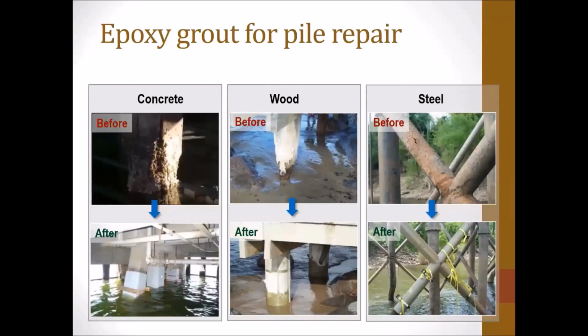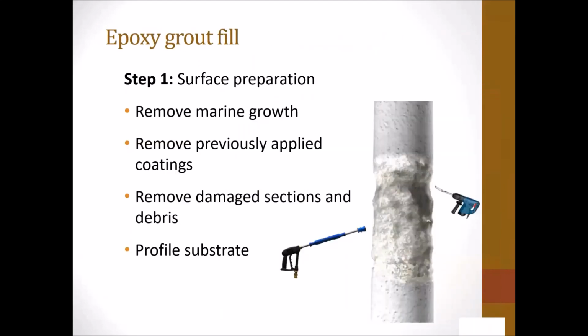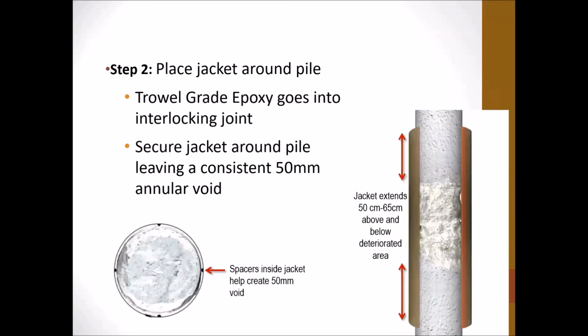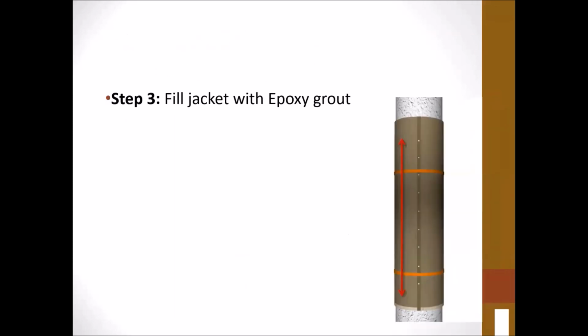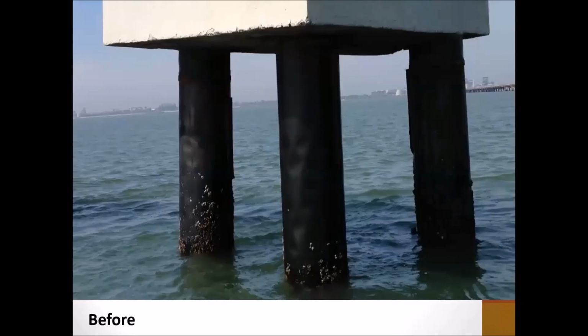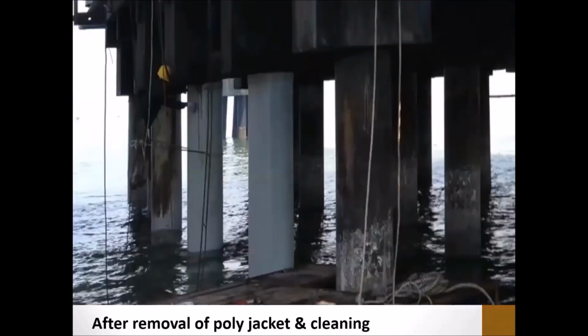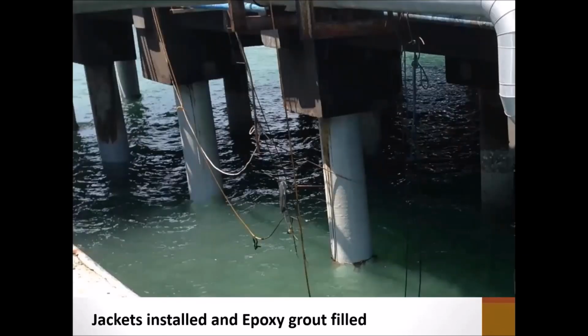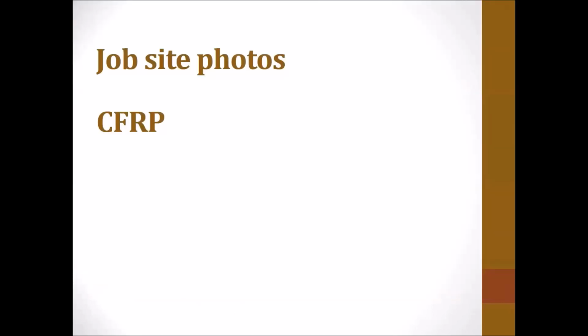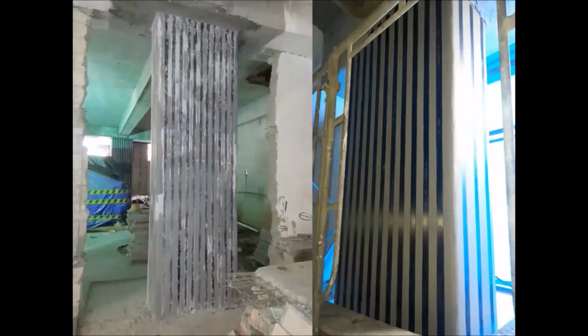So we can use epoxy grout for pile repairs. Basically we have to think about that only. We can use the fiberglass jackets after the surface preparation, and just fill the fiberglass jacket with trowel grade epoxies. So this is before, in the marine structure. After removal of poly jackets and cleaning, we can install the fiberglass jacket and fill it with epoxy grout. These are job site photos.